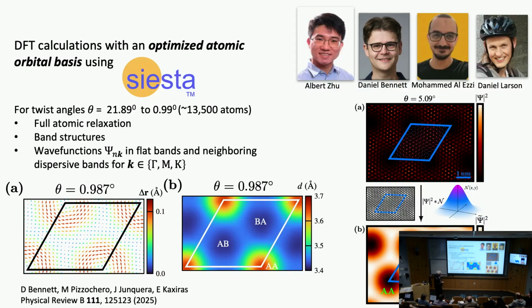So this is a picture of the Moiré cell, the blue outline here, at a 5-degree twist. That's a relatively large angle twist, and the reason I'm showing you this is because at this relatively large twist, the Moiré cell is relatively small, so you can see the atomic positions. Those are the little blue dots here, which are the atomic positions. That's the Moiré cell. And the little speckles here are the weight, absolute value square of the wave function. Because it's hard to see all this detail, we do a convolution of the wave function with a Gaussian. So you see sort of the average of the wave function magnitude spread over all of the Moiré cell. So that's what this wave function convoluted with a Gaussian will look like on the Moiré scale.